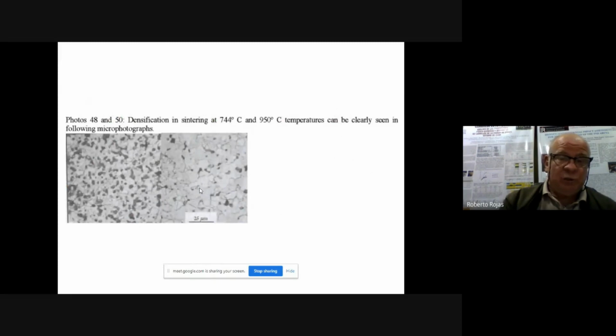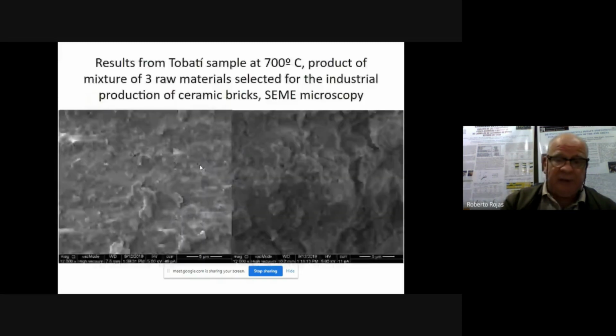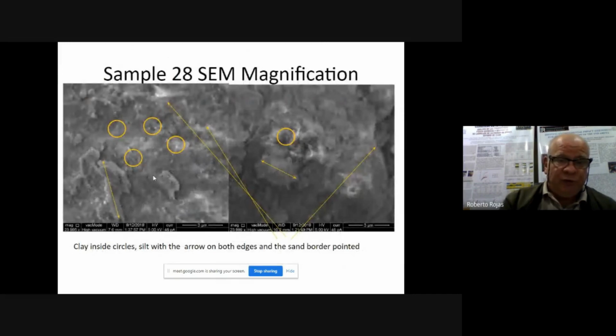The densification we see in these materials is more when we have more centigrades. Here, the densification is even greater. We have also taken some SEM microscopy, and we put the clay in little points. This is the silt, and these are the sand borders. The sand borders are these. We have here the sand borders.